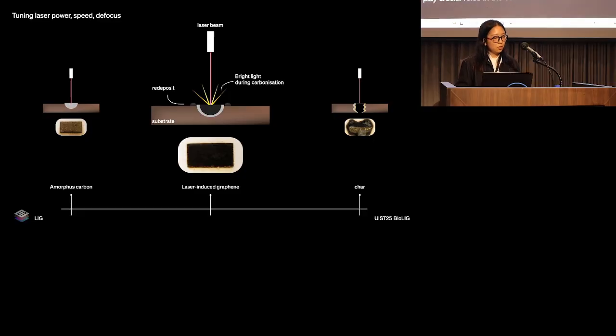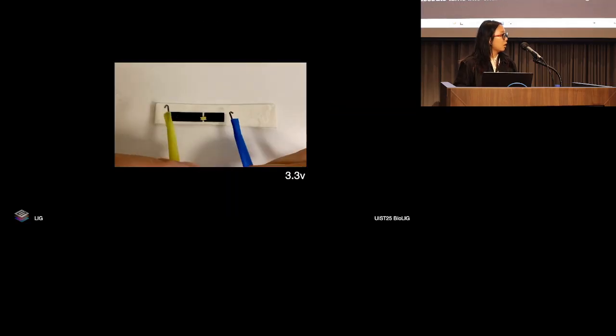The power, speed, and especially the defocusing of the laser play crucial roles in the successful formation. When you've used a laser cutter, you should be familiar with these settings, but there are a couple of visual clues that you can look out for. When there's not enough power, as you can see on the left, the formation is incomplete, resulting in amorphous carbon, and when there's too much power, the substrate turns into char or can even burn through. At the optimal laser setting, one can observe bright light during the carbonization and is then left with a dark gray to black layer of laser-induced graphene that is conductive.